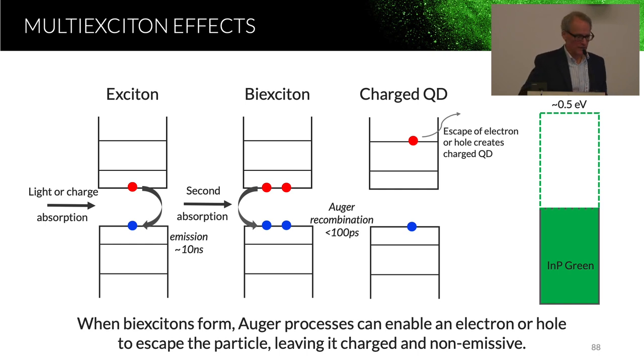So instead of having one of these still present, this recombines and gives the energy to this one, and now it's got twice the energy. And why is that a problem? If we consider this green bar, the band gap energy for green, for instance, and this is the valence band, that's the conduction band, if you give it twice the energy, it's within half an electron volt of vacuum. And so this is a very highly energetic electron.